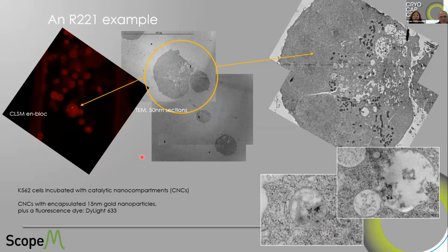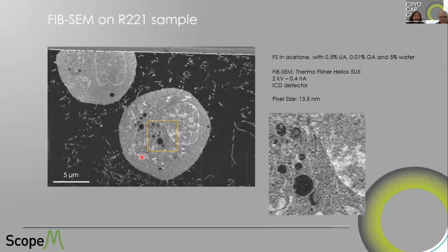So this is what I would recommend to go into. And you see, it also gives us a nice ultrastructure. This is a FIB cross-section. Even with this not perfect freezing, we do get to see all kinds of details with a very low amount of uranyl acetate contrasting only. And this is something that we have to highlight. You don't need so much uranyl acetate here, and you don't need osmium at all to get good contrast.